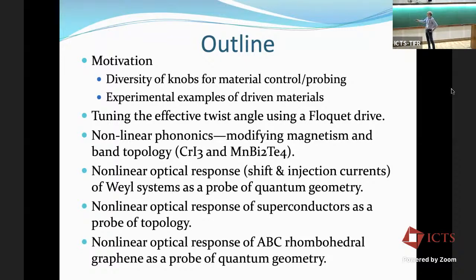Then I'll switch to talk a little bit about nonlinear phononics. This is where you tune the light frequency to resonantly excite certain phonons, vibrational modes of the crystal, but with a very high intensity light, so that you push the displacements of the phonons beyond a harmonic regime. So you have nonlinear effects, and you can use the excitation of one phonon to couple to another phonon, and it turns out that in some situations, that allows you to control the magnetism and even the electronic band topology in materials. And I'll give two examples that we looked at here, which are in thin film form, bilayers.